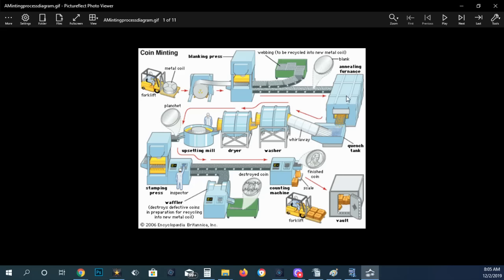Then it goes through the annealing furnace. In the annealing furnace, there can be other metal molecules that can adhere to the coin and the annealing actually softens the planchet a little bit. Then it gets into the quench tank, basically cools it off. Whenever it goes through this process and you've got the washer and you've got the dryer, sometimes a detergent or something can still remain on that planchet if it's not properly washed off completely. Sometimes that could be what causes milk spots.